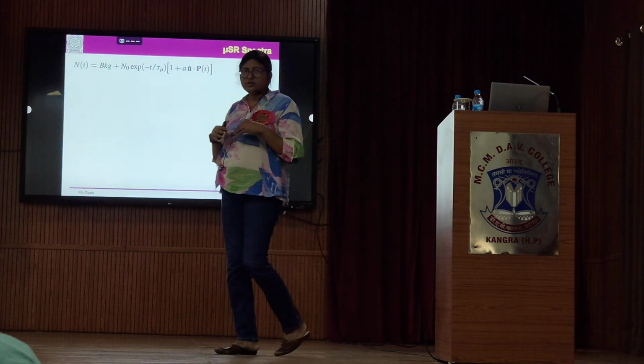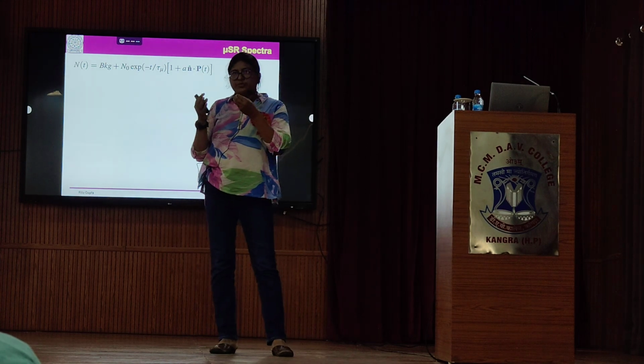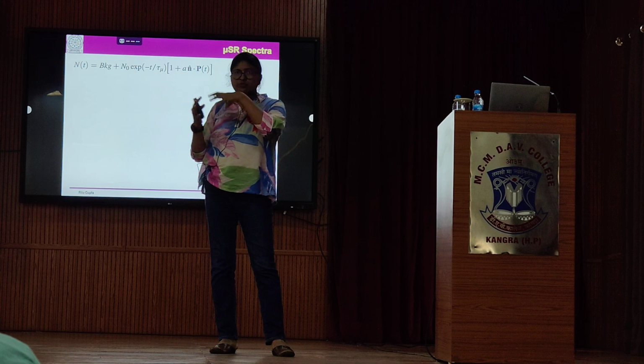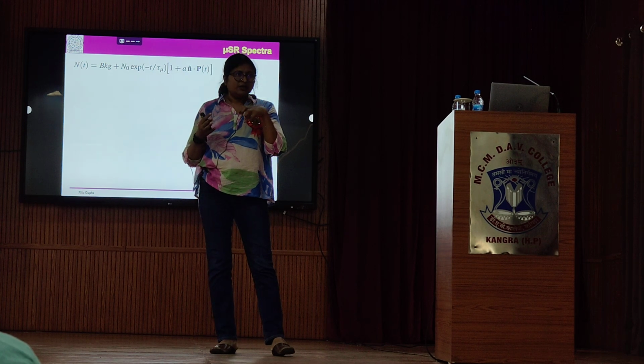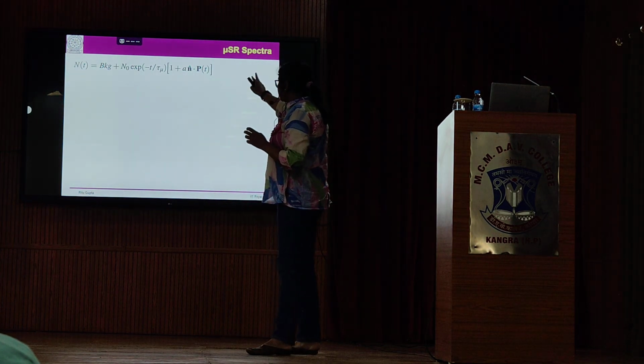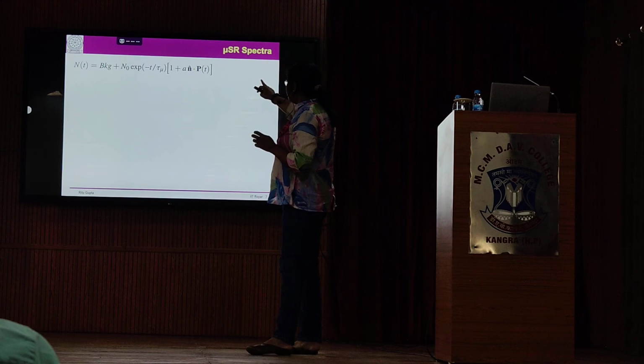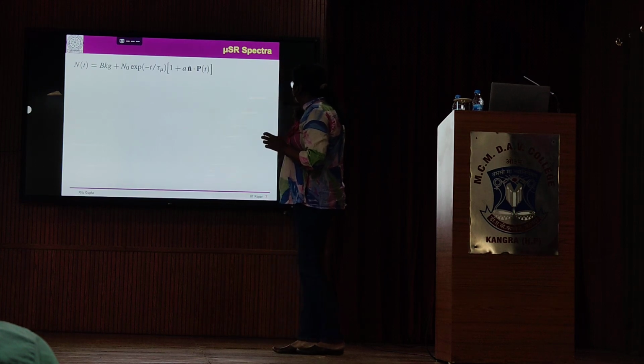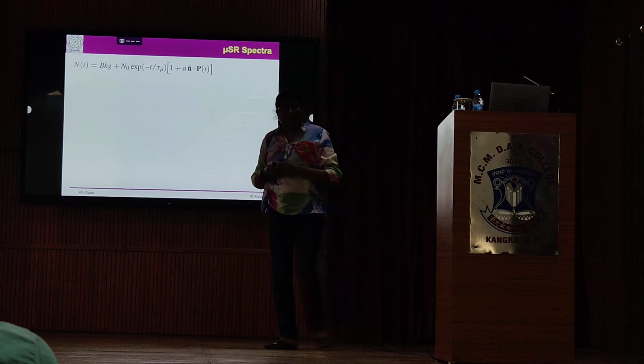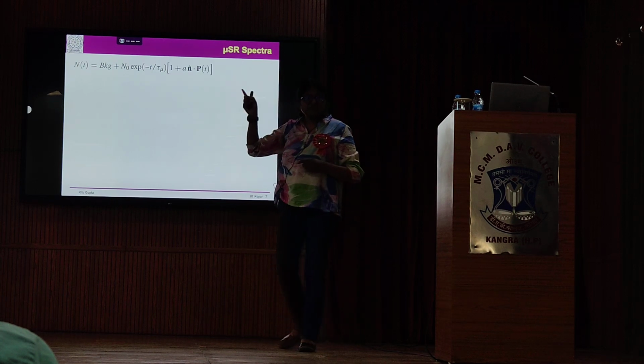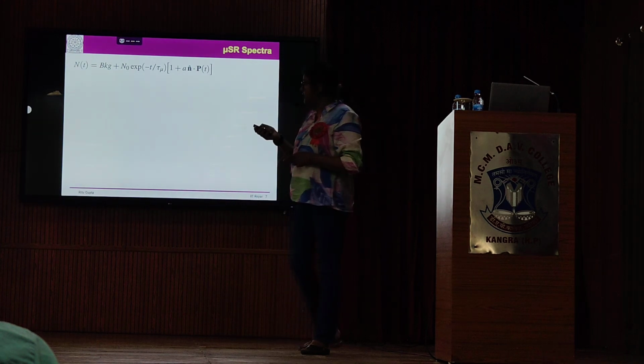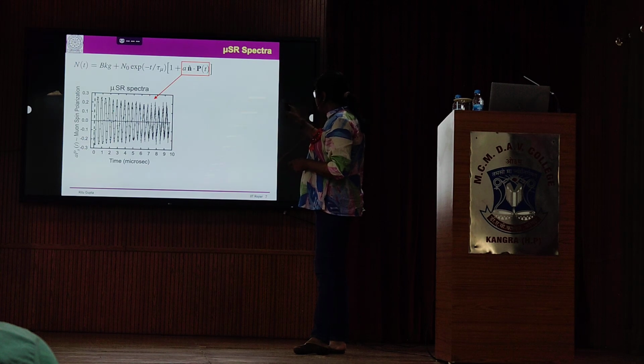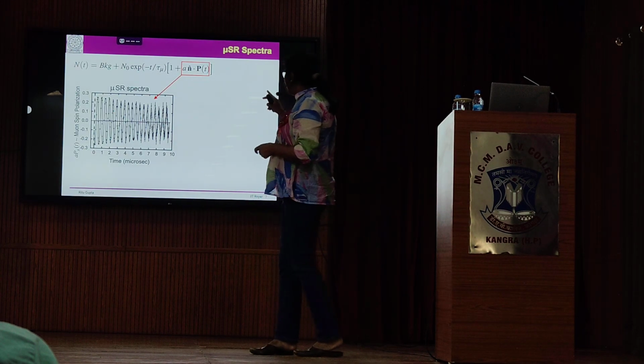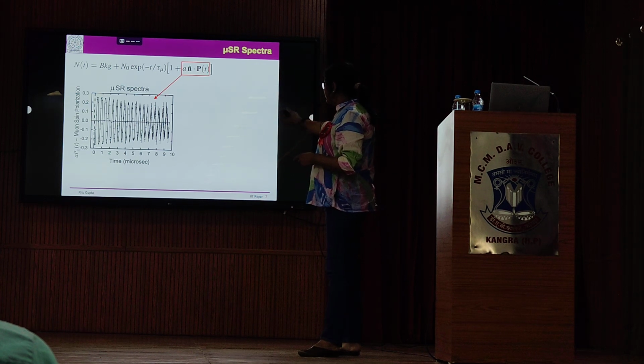So basically these are the number of positrons which are collected on a detector. Okay, so you basically shine your sample with the muon beam, and then you will have positrons, and those positrons are basically detected. Okay, and these positrons basically comprise this background term. Then you have a decay term from the muon decay, and then in the bracket you have this term P(t), which is the muon spin polarization, and n is the direction in which our detector is placed. Okay? So this kind of spectra you will get out of this experiment, and this spectra is showing muon spin polarization as a function of time.